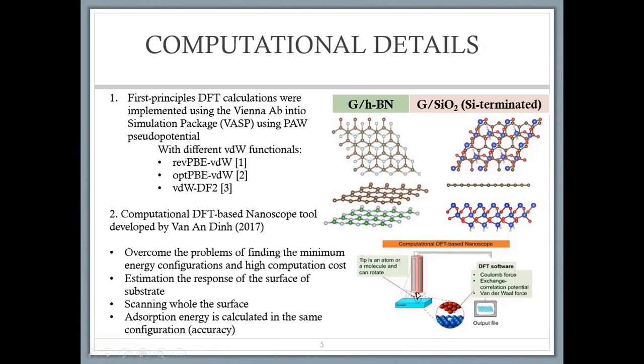By which the molecule will move on the adsorbent surface and rotate around its center of mass to find out the stable adsorption configuration. And at each configuration, we will apply the DFT simulation to find the total energy. So the minimum energy configuration will be determined. And not only a parallel rotation, but we can also apply a vertical shift to find the optimized structures.